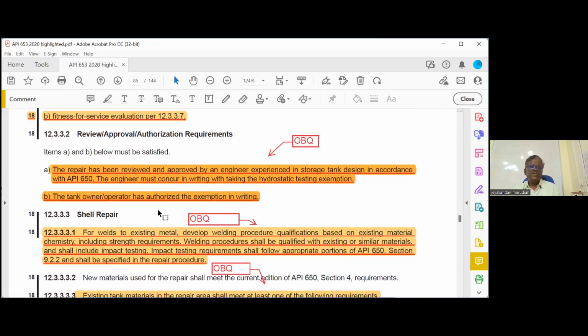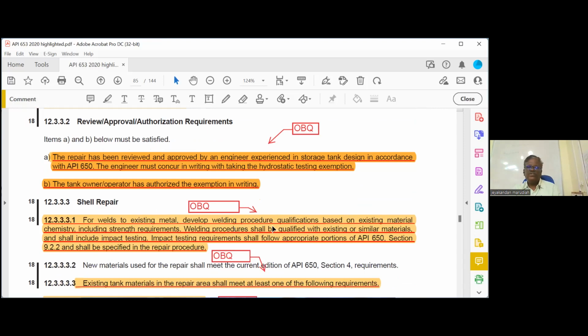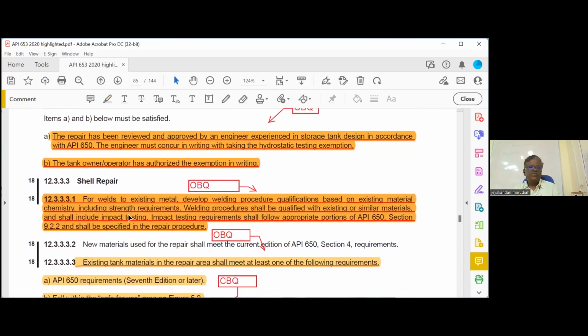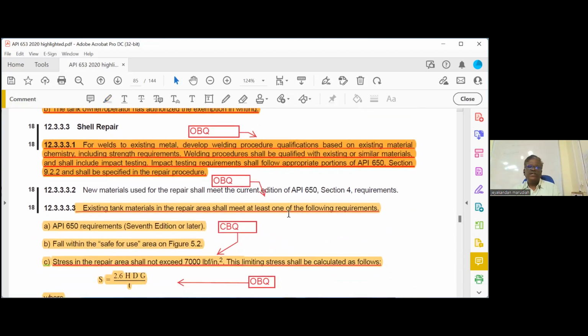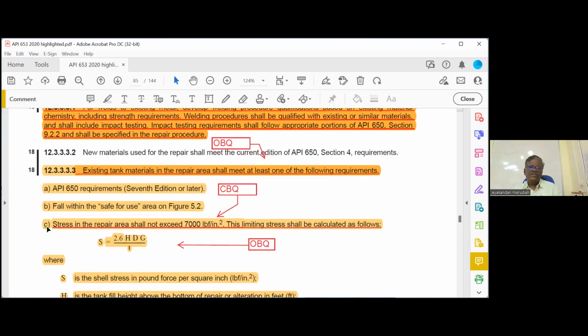Okay. What is 12.3.3? For welds in existing metal, develop a welding procedure qualification based on the existing material chemistry and strength. The welding procedure shall be qualified with the existing shell. First, we have to qualify the procedure for this repair. Then, the existing tank material in the repair area shall meet at least one of the following. The first condition is the 7th edition or later of API 650, or it should be any one of these conditions. Within the safe use 5.2, you know the exemption curve, it has to follow. Or the maximum stress of 7,000 in the repair area. This is very important.